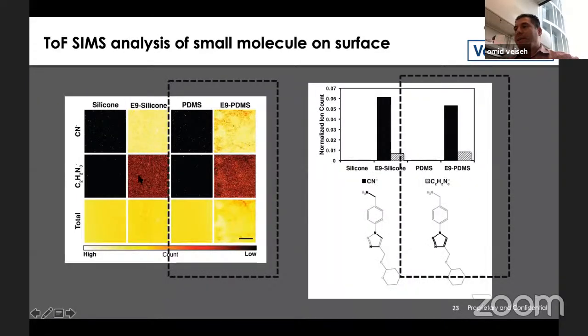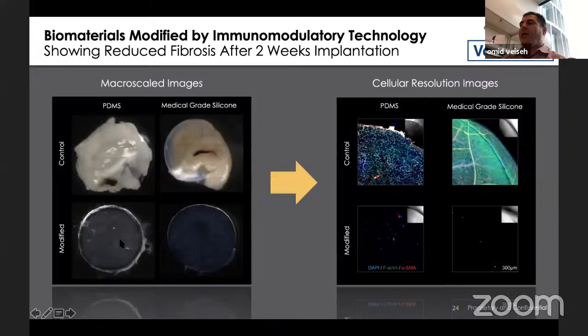These small molecules we can apply to different surfaces and really probe this mechanism further and understand what it is about these molecules that is giving this preferred response. So we switched to working with discs of different medical devices. Silicone, PDMS, these are polymers that are widely used by the medical device industry. We wanted to see what would happen if we attach our chemical modifications to the surface of these. We first quantified and showed that we have the coatings on there, and we implanted these into mice. Again, when you have the chemical modification, there's no immune response and no scar tissue formation. When it's just the material by itself, you get a pretty nasty scar tissue formation.